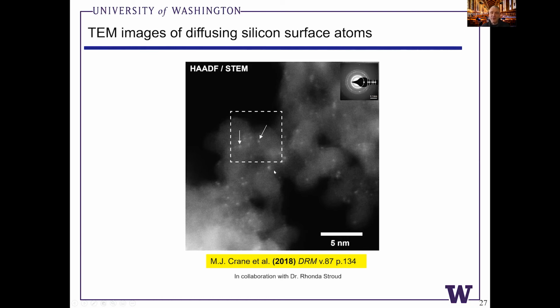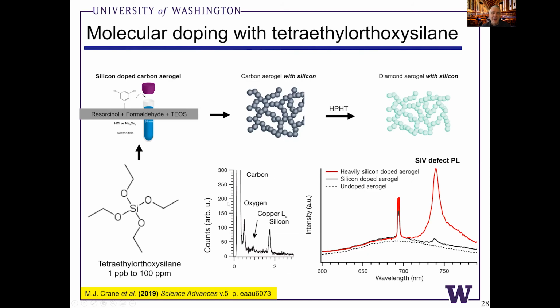But the next step was, could we deliberately add the silicon back into the diamond nanocrystals? So the approach that we took was using a tetraethyl orthosilicate molecular dopant. We added this in with resorcinol and formaldehyde, did the same type of gelation reaction in a plastic container. And then we looked at the X-ray fluorescence spectrum of the silicon doped material. And sure enough, we were able to see silicon atoms show up in this doped material, which we didn't see